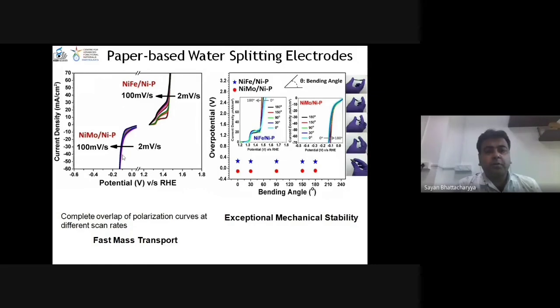Same, this is for the OER, that is oxygen evolution. This is for HER, the hydrogen evolution. And so they have a fast mass transport. Mass transport means the ions are moving very fast on the surface of this electrode. Okay, and this is the flexibility test. If you bend at different angles, you can see that it is a bending angle. You see the overpotential, that excess potential I spoke to you about, does not change, and that is constant as well. And they have exceptional mechanical stability.